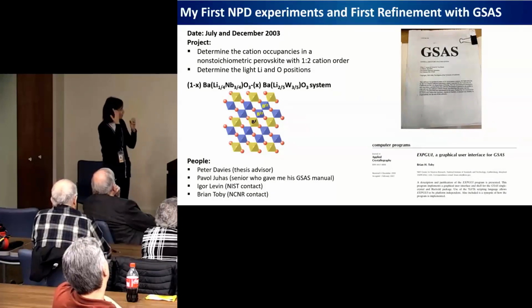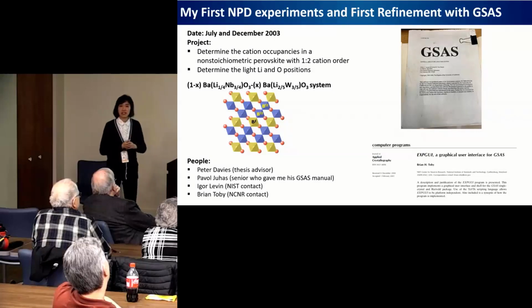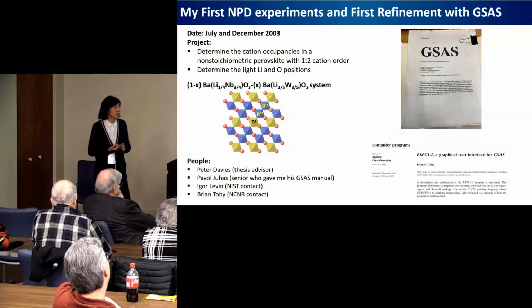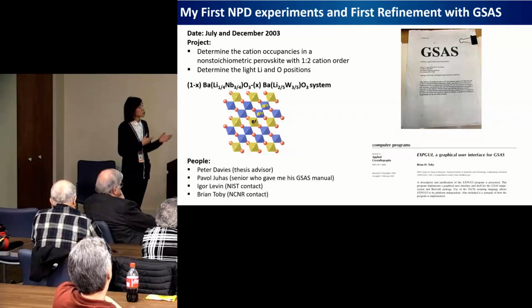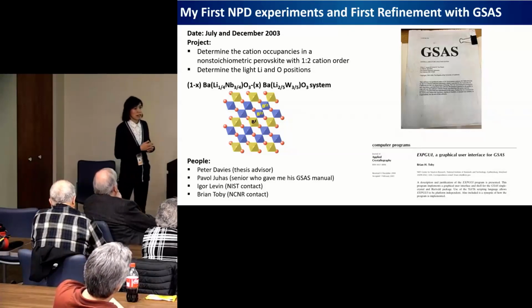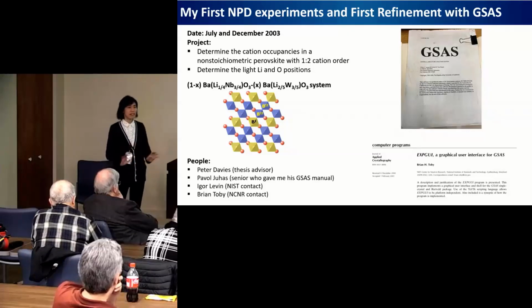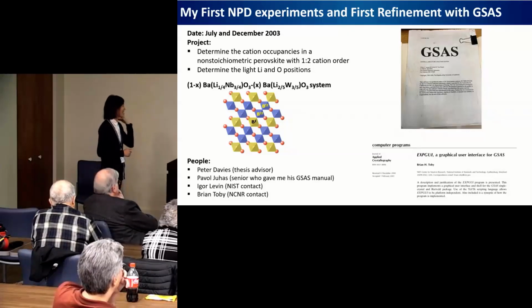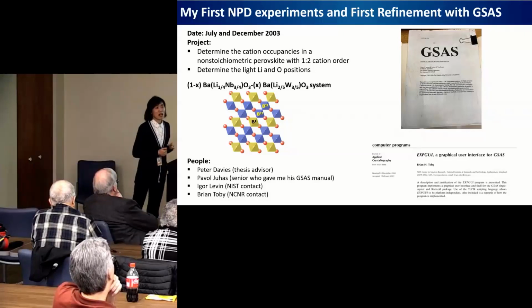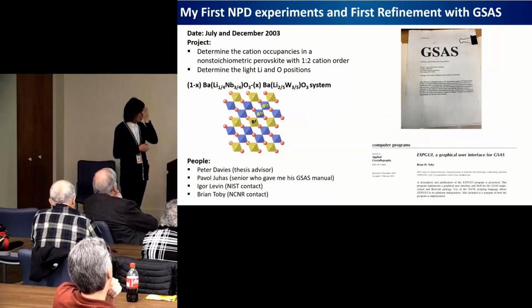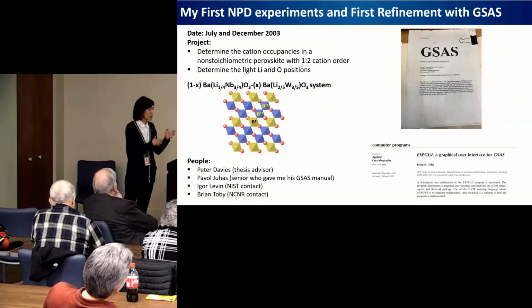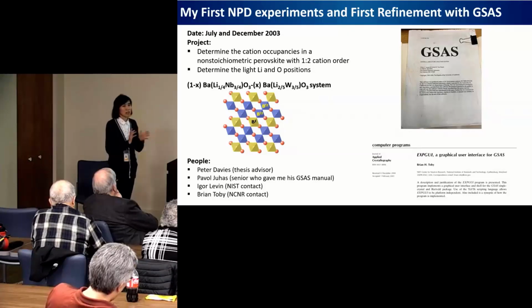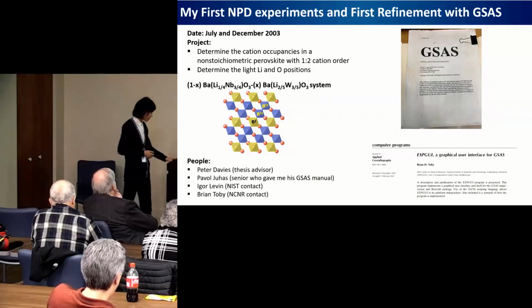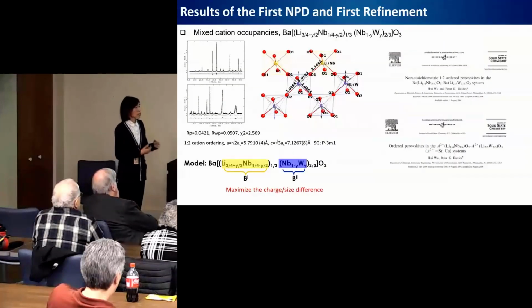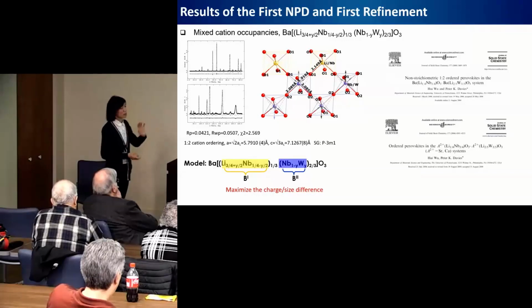Later, with help from Igor and Brian, who was in charge of BT-1 at that time, I successfully did my first neutron diffraction experiment. I got good data with the expected peaks from the superlattice, without breaking the instrument. Then I came back and started to learn GSAS. Fortunately, Brian developed the EXPGUI interface for GSAS, which is very friendly and makes the learning process much easier and quicker for beginners like me. I managed to teach myself GSAS and finally did the refinement.